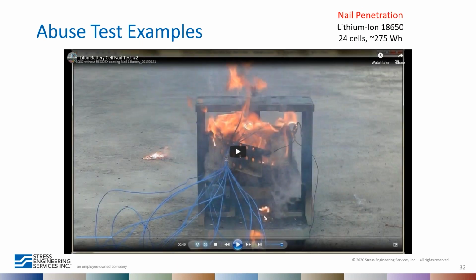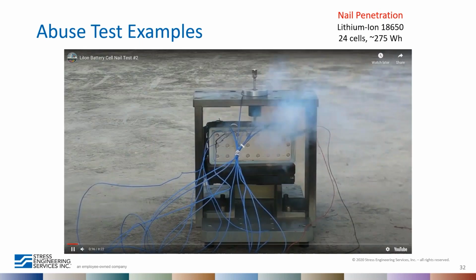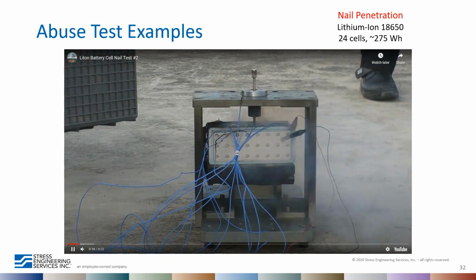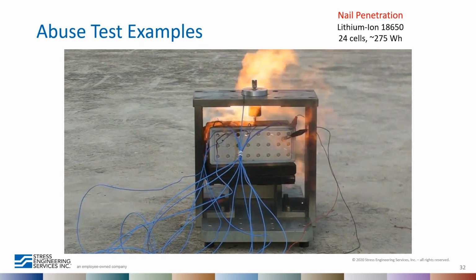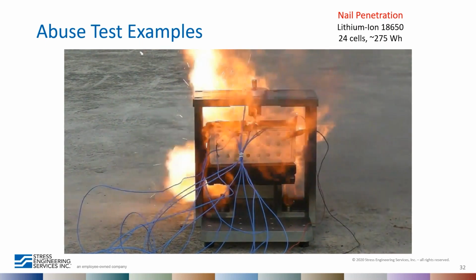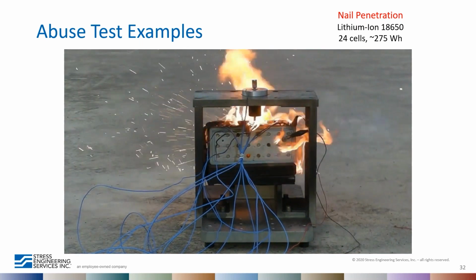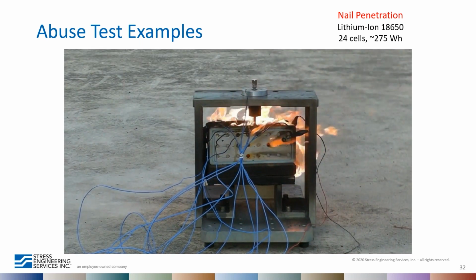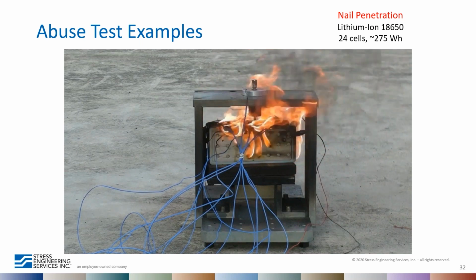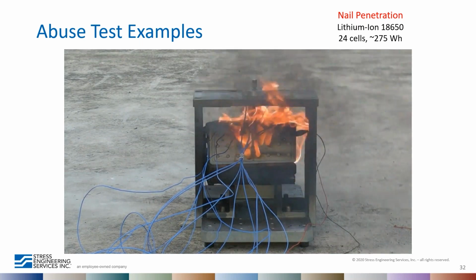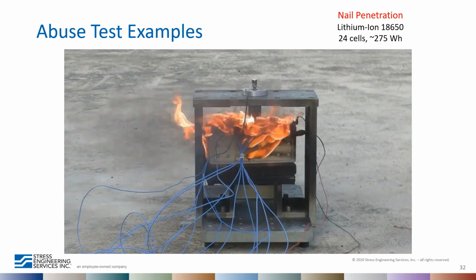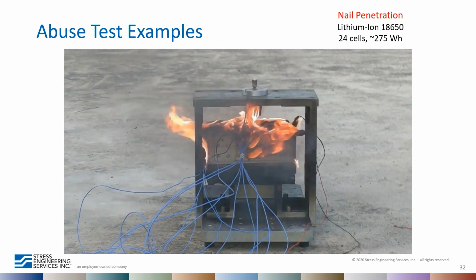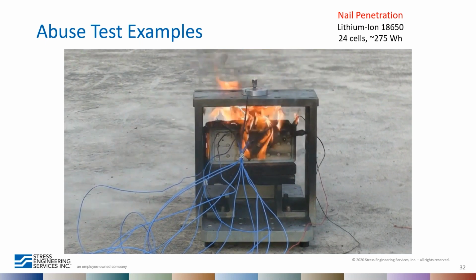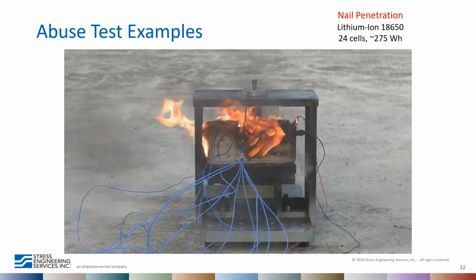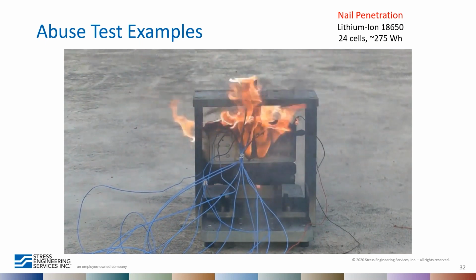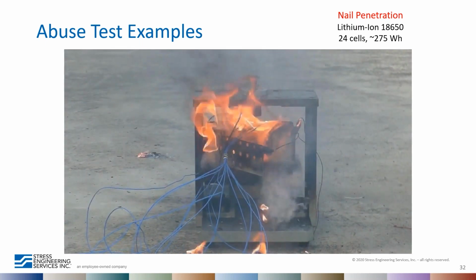And another example is a nail penetration test. So this test is really trying to simulate an internal short circuit instead of an external, where there's a manufacturing defect inside the cell, and it leads to a puncture of the separator and short circuit. This is a multi-cell test with 24 cells, so we also see the effects of thermal runaway propagation. This is using a nail penetration style device, but there are actually cells that have been developed today that have built-in internal short circuit devices that melt the separator inside and are more controlled.